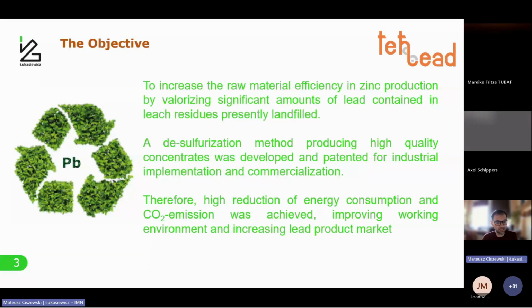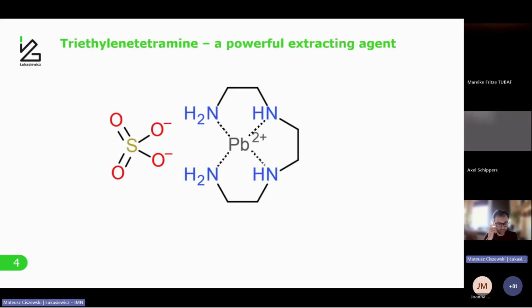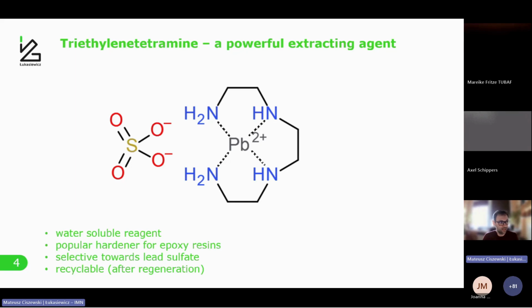We used the so-called desulfurization method, which allowed us to diminish energy consumption and the negative impact of emissions of toxic gases. So our magic substance was TETA, triethylene tetraamine, which is a very powerful and very selective extracting agent toward lead sulfate. Other lead compounds are quite inactive, but for lead sulfate, the aqueous amine solution allows us to extract lead sulfate into the aqueous phase.